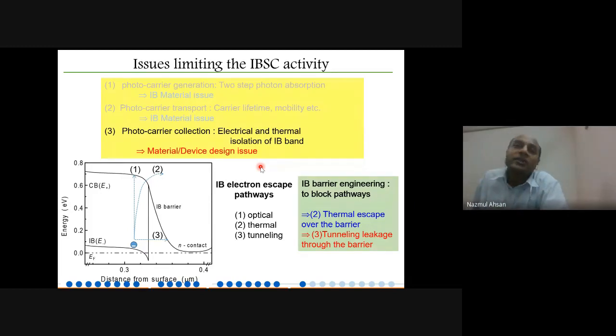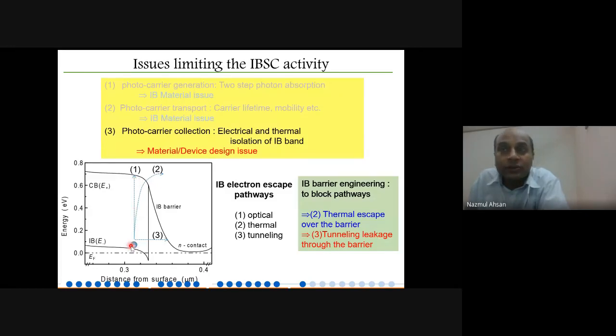The main challenge when you make your material into a device is in your intermediate band: if you excite the electron in the intermediate band, the electrons can escape to the contact directly. There are different kinds of pathways of the intermediate band. What we expect is process one, that you excite the electron by some long wavelength to the conduction band. But what happens most of the time is that before going there, it tunnels through to the conduction band. This is called tunneling loss.